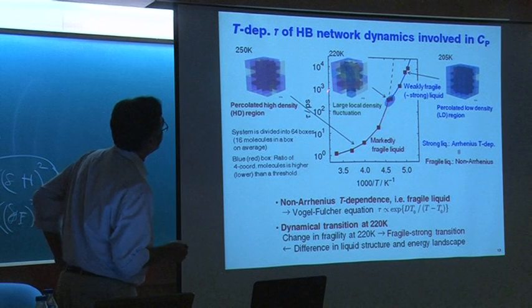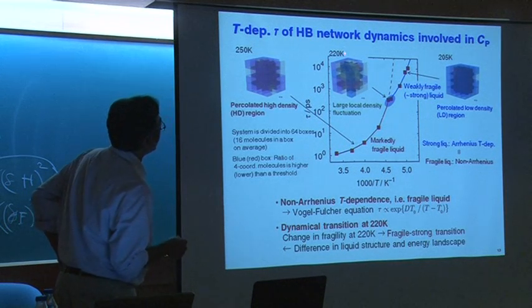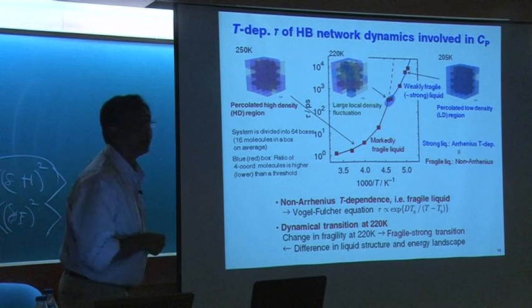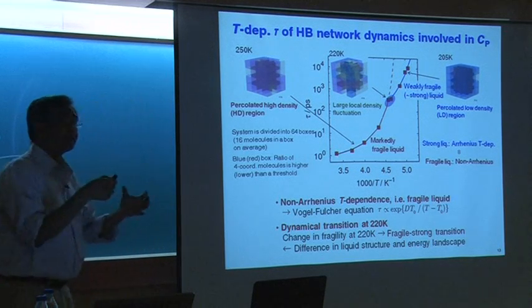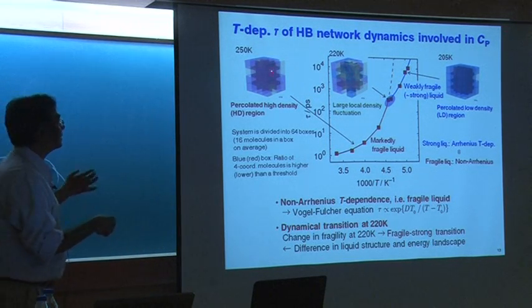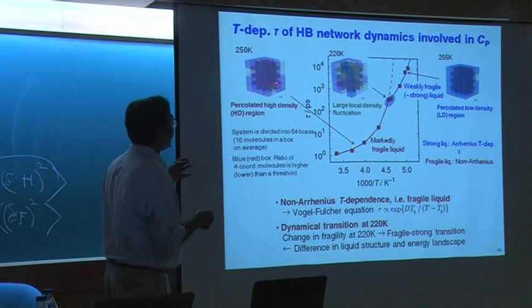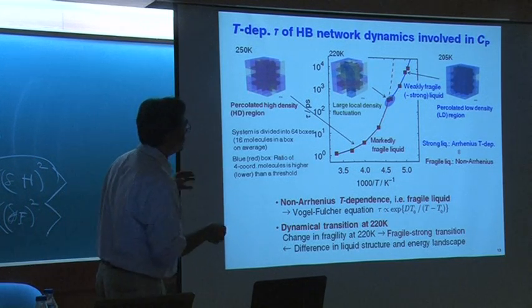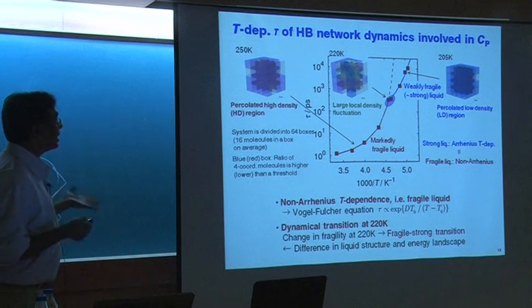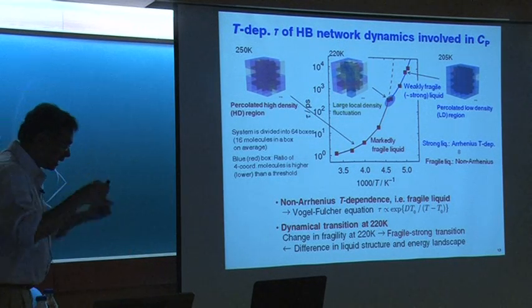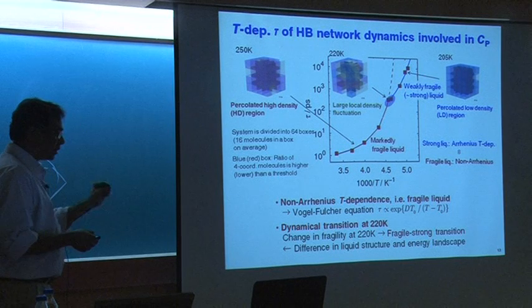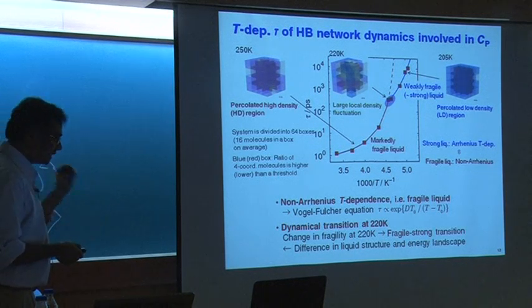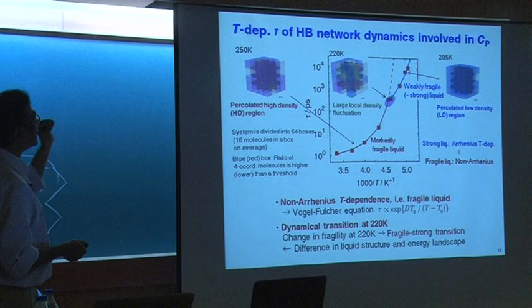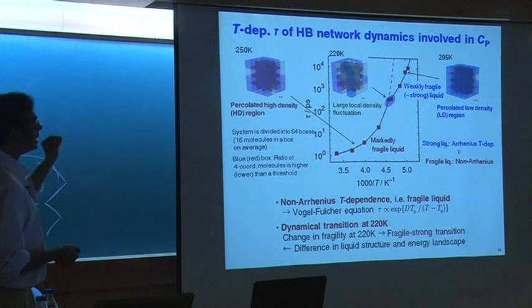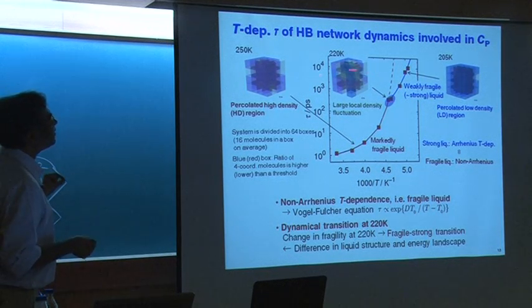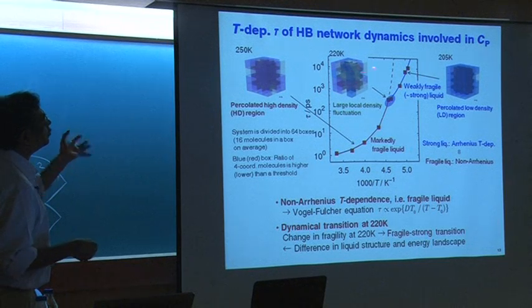At 220, the movie would have been working. Red is high density, blue is low density. You would have seen large density fluctuation between high and low density. At 220 Kelvin, this is called a coarse-grained description. I have taken each box, divided the system into 64, 4 by 4 by 4, and then calculated the average density in each and assigned it as a high density liquid or a low density ice-like liquid. You would have seen very rapid fluctuations going between red and blue.